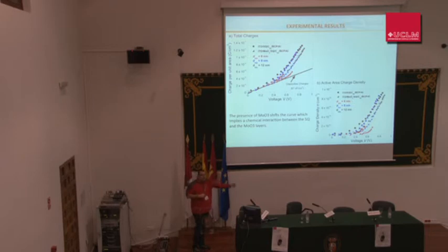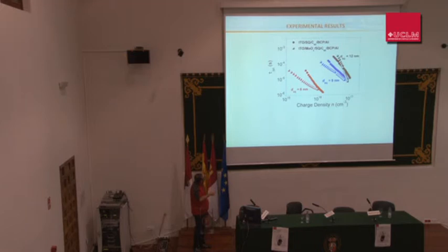The more voltage you apply, the more charges you have, because it's field dependent. But it's exponential, meaning that this is the tail of the density of states. Organics have a density of states which is like a Gaussian, okay? And this is the tail, the last part of the Gaussian. The Gaussian will be like that, and you're filling only these states. You cannot fill more because the more charges you have, the faster is the recombination. And that's what you have to work on. You have to increase the charges, but making this number slower.